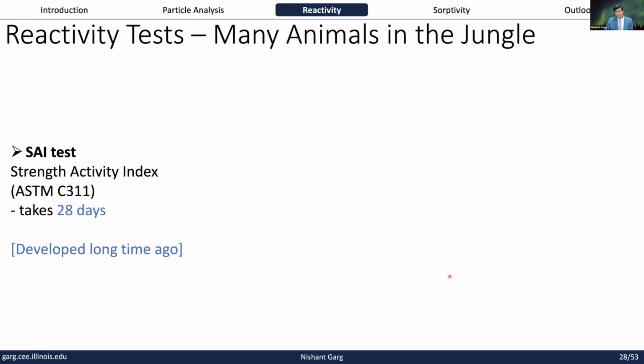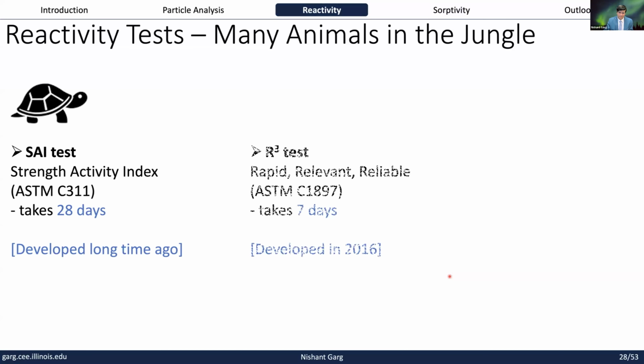If you consider the reactivity test, there are many animals in the jungle. So there's the SAI test, which is very common and very popular. It's the gold standard in the industry, and is part of the ASTM standards as well. Then about 10 years ago at EPFL, this R3 test was developed, which was really a game changer. It cut down the testing time from about 28 days to 7 days because it could very well predict that 28-day SAI in a week.